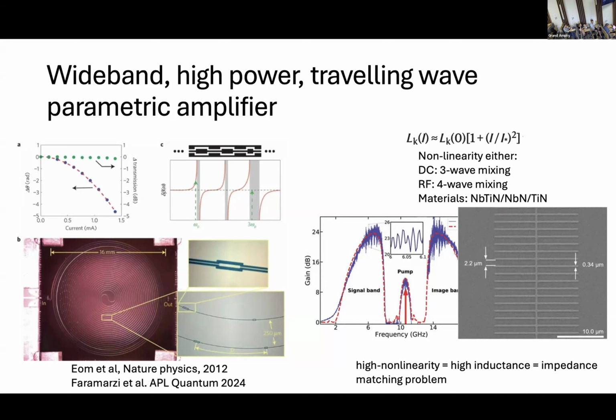Because technically with aluminum, you can do really easily planar aluminum, oxide, planar aluminum, oxide. Well, because the oxide is also lossy. We can argue how lossy it exactly can be before this becomes a problem, but there are actually microstrip versions of this as well, where they do just 2 layers of nitride with a dielectric sandwich in between. And if the dielectric is of high enough quality, then that's fine. And this actually makes the impedance thing easier because you don't have to do so many crazy structures. But that has been done, but I can't recall the reference from the top of my head.